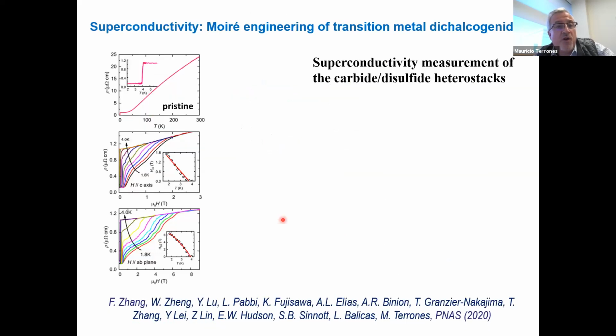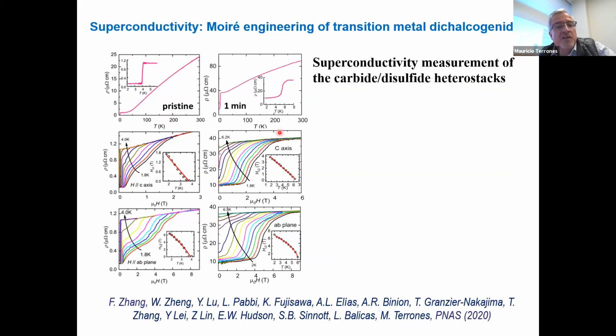So one thing that we looked at is the superconductivity here. And this is a superconducting transition of the molycarbide flakes that we make. So beautiful, very sharp transition. That means it's a very pure system, very pure phase. But then instead of 4 Kelvin, when we have the 1 minute, we start to see an increase in the TC to 6.5, close to 7. So we increase the TC just by having this sort of system which has gamma prime and alpha molycarbide.